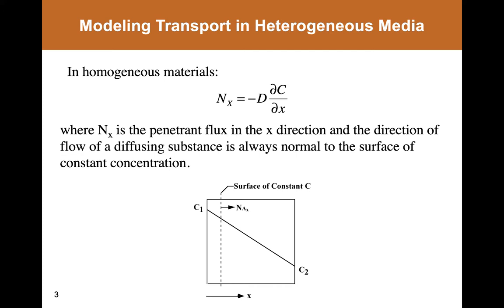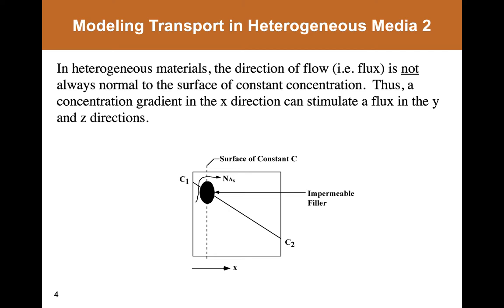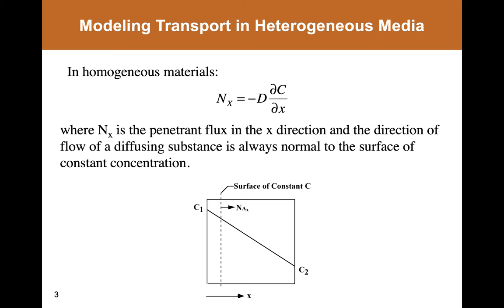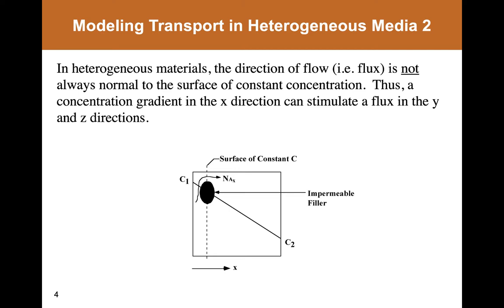Now, typically in homogeneous materials, we would start with Fick's law to describe the flux of a penetrant in a direction under the influence of a concentration gradient in the x direction. And if an impermeable filler, for example, is added to such a material, then any penetrants that are diffusing down that concentration gradient have to go around the filler, and as a result, there is a component to the flux that is not aligned with the concentration gradient. And so what we normally think of as Fick's law is that a concentration gradient in one direction stimulates or brings about a flux in that same direction. When the material is heterogeneous, then a concentration gradient in one direction can bring about a flux that is in the direction of the gradient, but also in the directions that are perpendicular to that gradient, as shown in this figure.